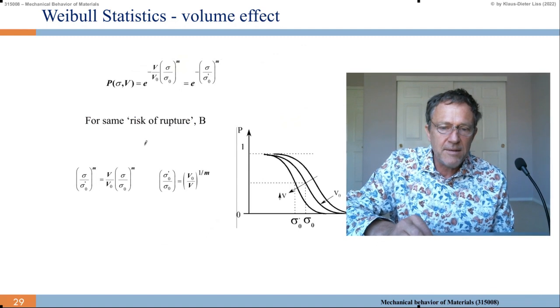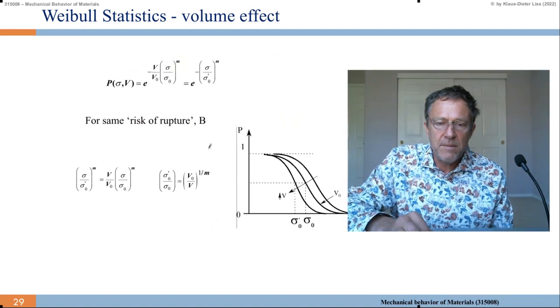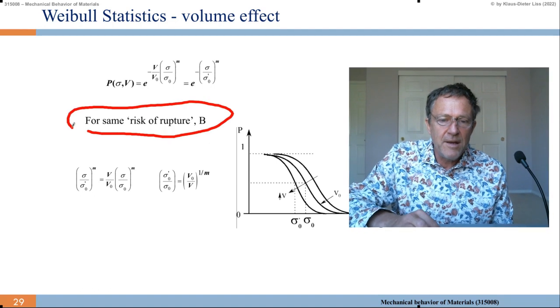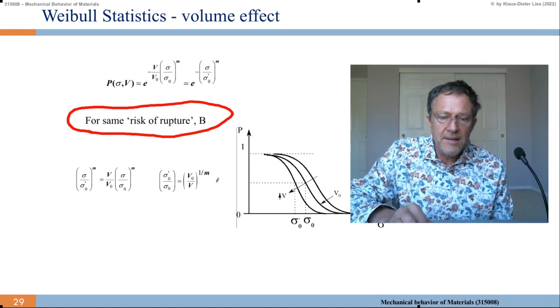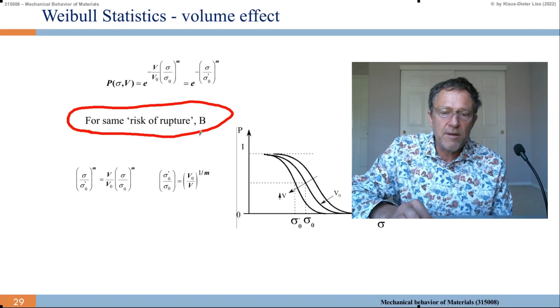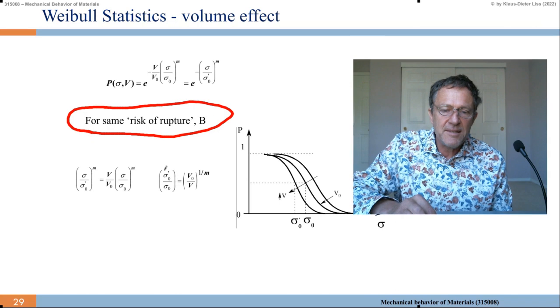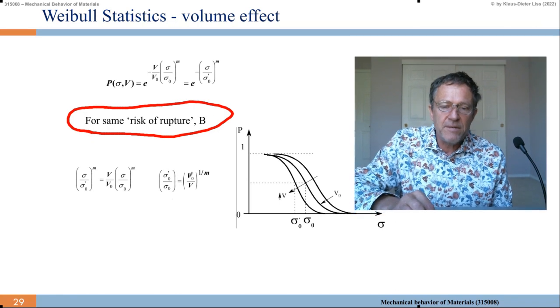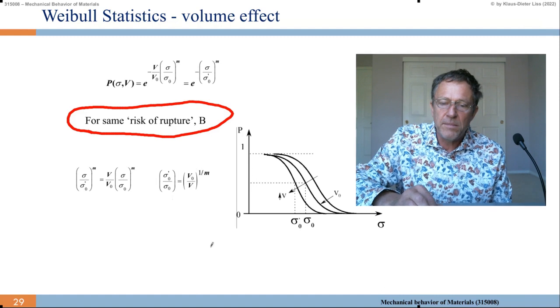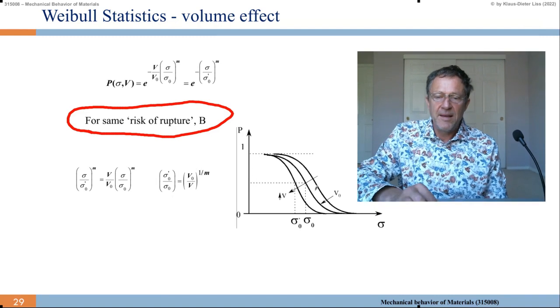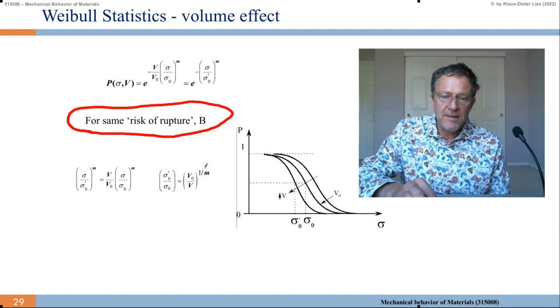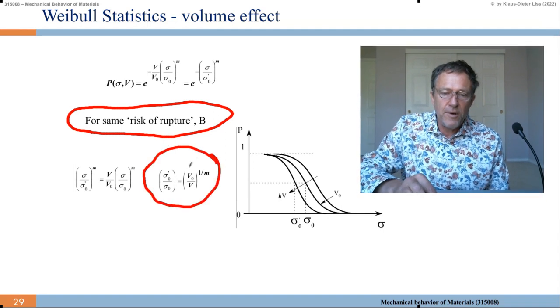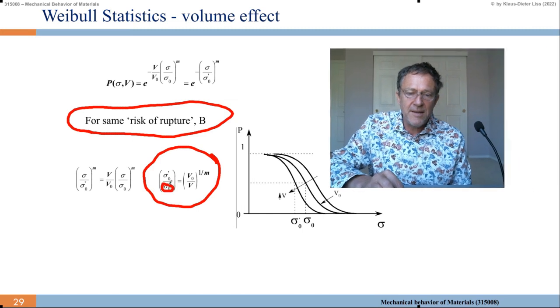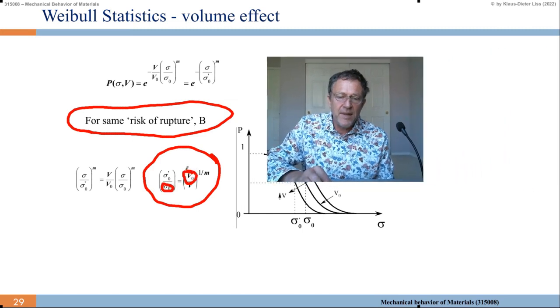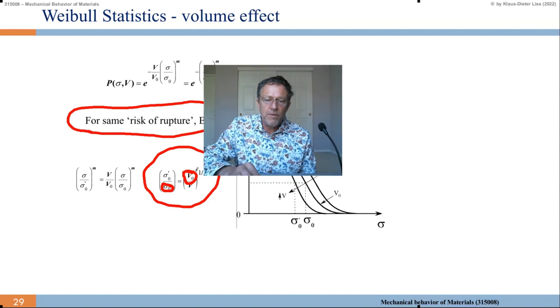I think this is really the same thing that I said before. If I design with the same risk of rupture B, then the stresses sigma prime over sigma 0 scale with V0 over V to the 1 over m. So for a given risk of rupture, I shift the curves as shown here. And it scales inversely. So I have the V0 here in the denominator, I have the V in the numerator. So it scales inversely with the volume to the 1 over m. This is scaling you need to remember.